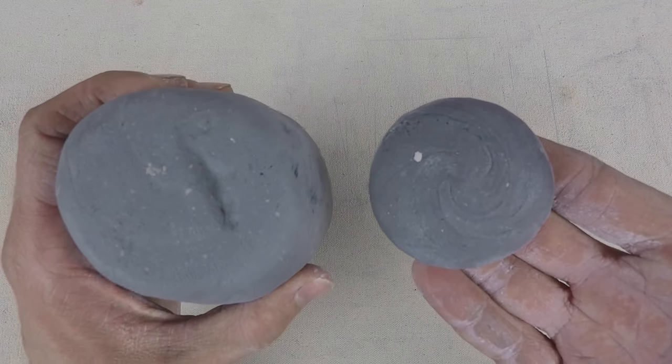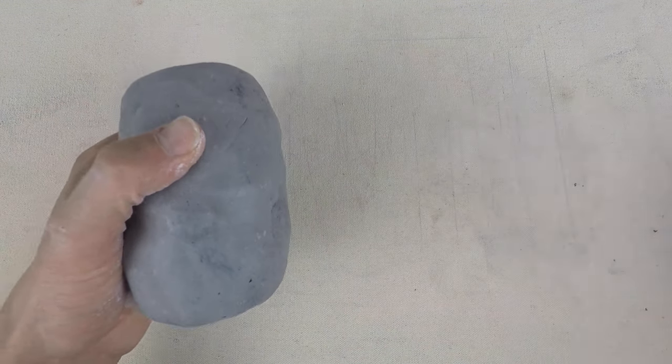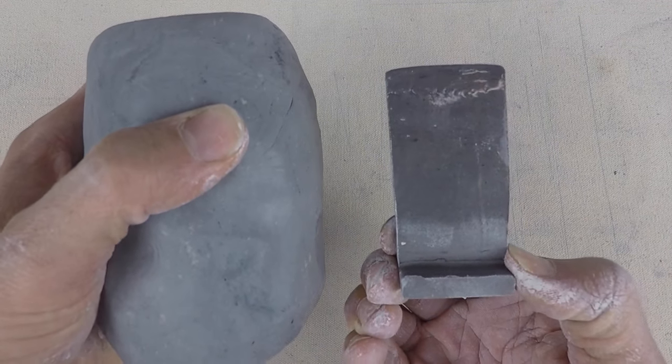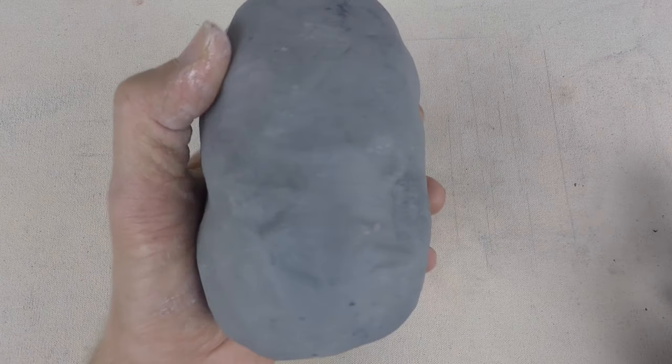Here's a little pebble I made — your normal test tile. No glaze. Then here's one with clear glaze on it, so it's a little bit richer, a little bit deeper with a clear glaze. You can see I didn't wedge enough for this first batch, so those streaks in there are big chunks of mason stain. This one should be a lot better.